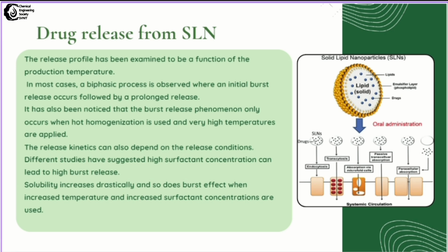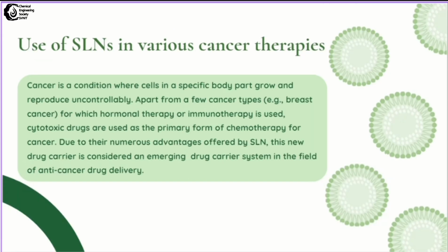The release kinetics can also depend on the release conditions. Higher surfactant concentration can lead to higher burst release. Solubility increases drastically, and so does the burst effect, when increased temperature and increased surfactant concentrations are used.